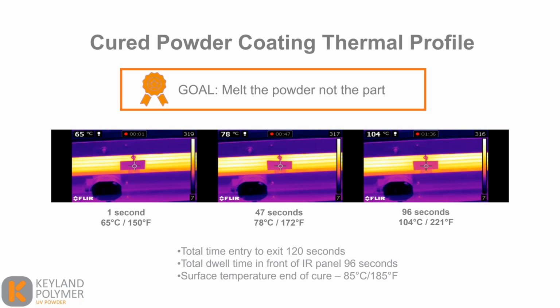So going back to that original goal of UV curable powder coatings, to only melt the powder and not the part, we have 3 images here of a polycarbonate plastic material that has been powder coated and then put into a gel oven, which is a medium range gas catalytic IR oven, for a total time of 120 seconds. At 96 seconds, that's when the part has been sufficiently flowed out. The surface of the coating only reaches 104 degrees C, which is enough for the coating to flow. We measured the temperature of the coating post-cure, and the surface of the material as well, which was only 85 degrees C. So the material itself was not deformed or warped in any way, shape, or form.